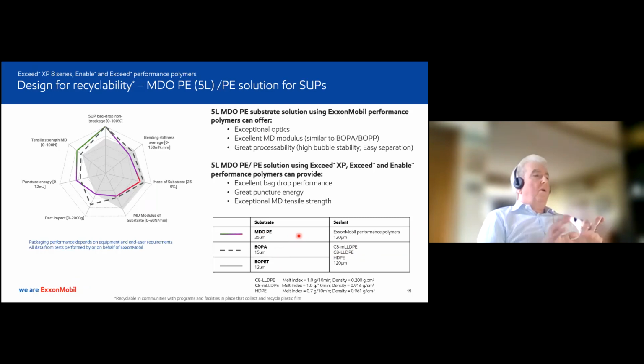Now, you'll notice the MDO is about 25 microns in this case. Obviously, it would start off a lot thicker than that, probably around the 125, 150 micron mark. The nylon or the BOPA is typically 15 micron in the industry, and polyester is typically 12. So we're competing here against known gauges in the marketplace. And if you look at the radar plot over here, you'll notice that even on the bending stiffness with the MDO, we're still able to achieve pretty good performance. It's not quite as good as the polyester, and the nylon sits in between, but it's pretty darn good. So that's actually a very pleasing result.